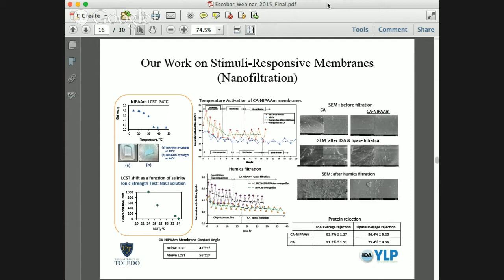And I know this is an incredibly busy slide, and I'm not going to go through every single part of it, but this is just our work on isopropyl acrylamide, on stimuli-responsive membranes using nanofiltration membranes. We make them responsive to temperature. And what I want you to look at, if the mouse does show, are just these SEMs here on the side. That first I have the clean membrane. This is the clean, regular cellulose acetate membrane. We like cellulose acetate because it's just really easy to activate. Next to it has one of the membranes that we have developed with this activation.